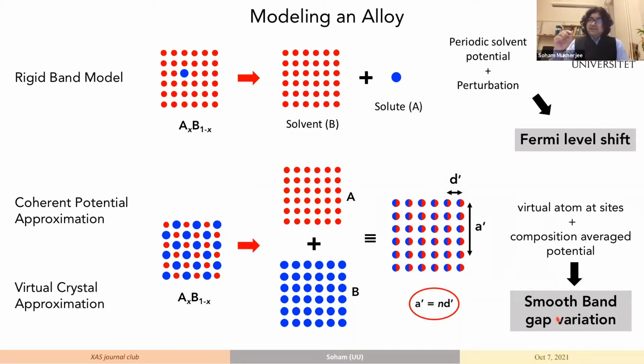But what it essentially does is, Vegard's law talked about variation of lattice parameters. It didn't go down to atomic connectivities. What these essentially did is to reduce Vegard's law to connectivity between two atoms. So what you can see is that you have a lattice parameter of an alloy, which is A prime. So the distance between two atoms can now be used as a multiplicative factor of the lattice parameter.